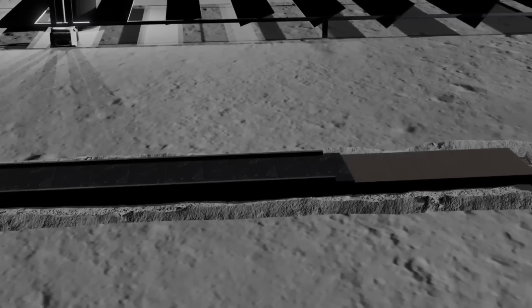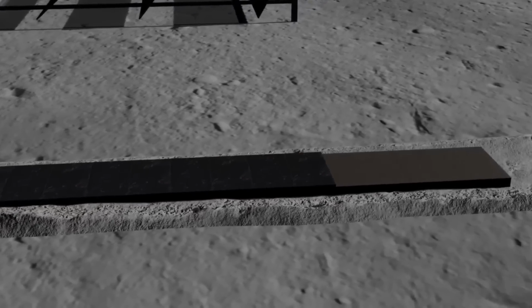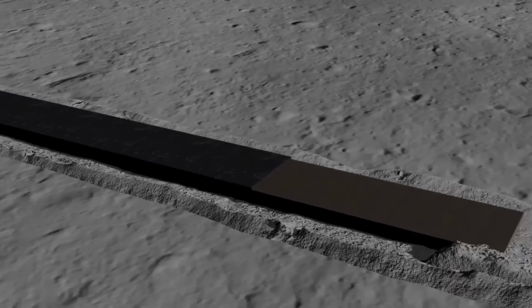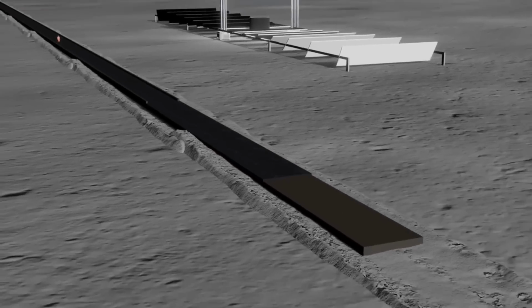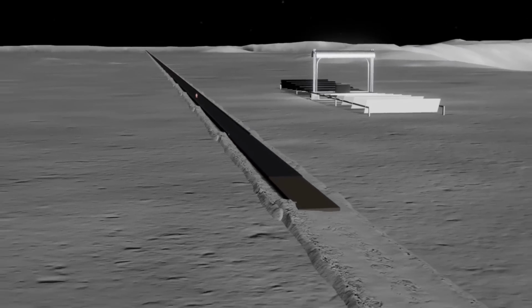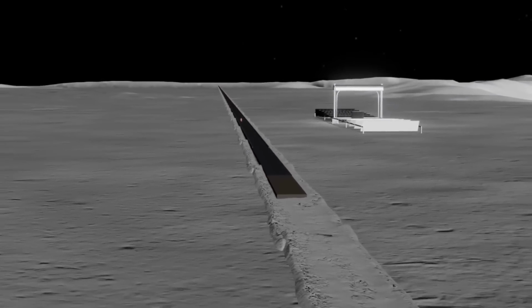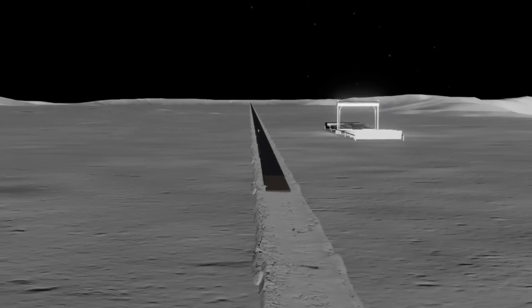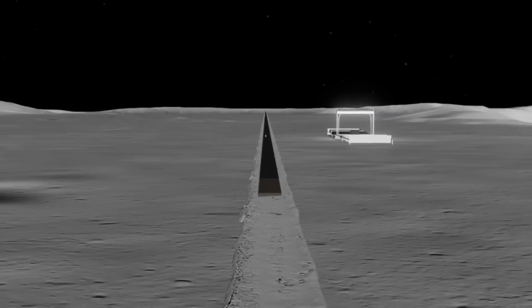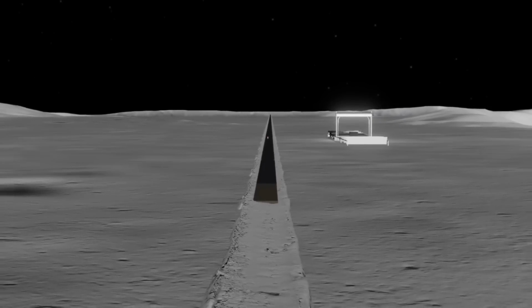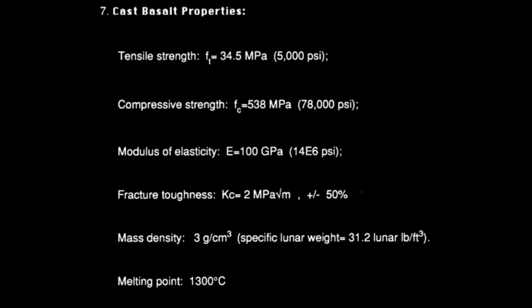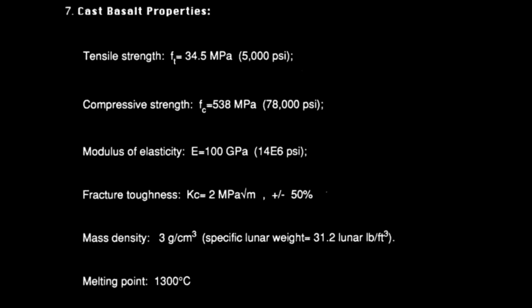So we are talking about paving sintered regolith plates or slabs on top of a cast regolith subbase, similar to how we pave roads today. And this cast regolith subbase will serve to absorb shock impacts, as cast regolith has about 5 times the compressibility of concrete and even sintered regolith, and a higher tensile strength, so it will serve to dampen what impact shocks do occur. But if cast regolith has these better properties, why even bother with the sintered stuff? Why not use the cheaper cast regolith for everything?